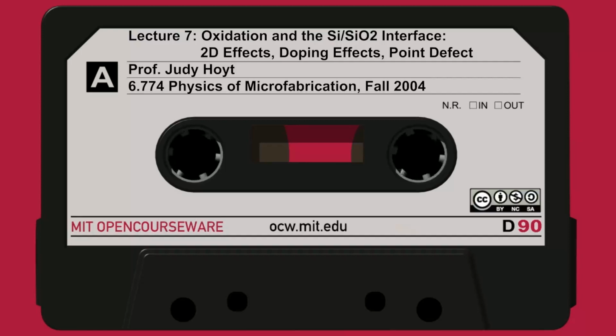Okay, let's go on to slide number 9. Just as shown in your text, I'm summarizing the impact of stress on our basic oxidation parameters that we know from our Deal-Grove-like model. The parameters from Deal-Grove, K sub s, the reaction rate, D, and C star all get modified in a way that depends on the stress in an exponential fashion, over kT. So it's very sensitive, and the stress effect will be different at different temperatures. So these parameters, VR, VT, VD, and VS, their reaction volumes, they're designed in Suprem 4, they are put in as fitting parameters.